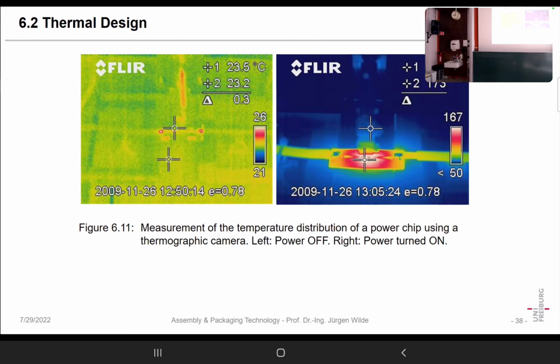If you don't have that paint, you have a problem, as on a semiconductor you have different locations, and each location has a different emission factor. One of the effects is that even if the temperature is uniform, it appears we have hot spots, but in fact that's not hotter, those materials just have a higher emission coefficient. You can also do that before operating the semiconductor. You put it on a hot plate, you determine the emission factor for every pixel, and later on you use that emission factor for every pixel. Of course, you must not move the image in between.